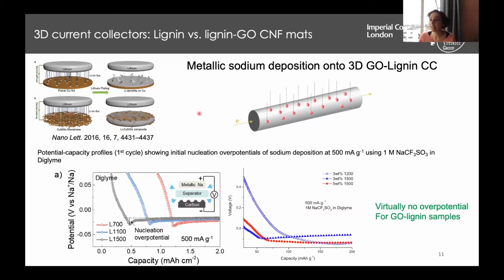So we have identified that there are two main important factors in how these three-dimensional current collectors behave. It's not only about the number of defects that we have for promoting the nucleation of the metal, but also about the conductivity of the whole scaffold. So we've done continuous plating and stripping of sodium on our carbons in diglime, which is a very stable solvent, using sodium CF3SO3, a 1 molar solution.